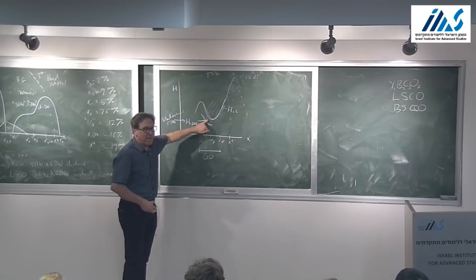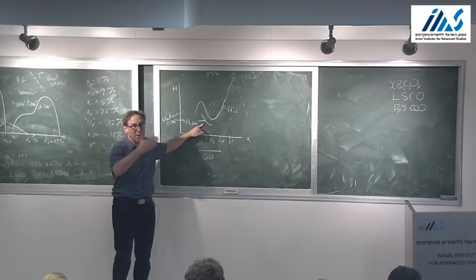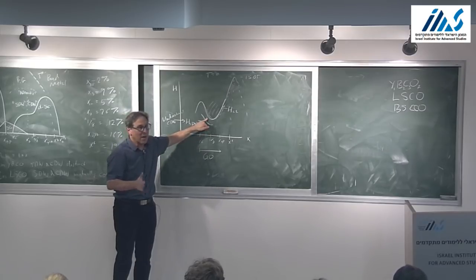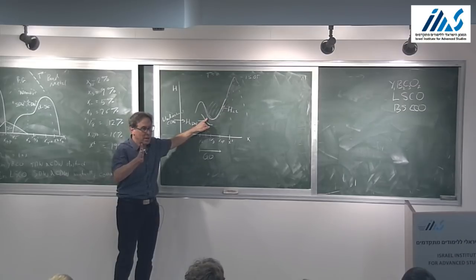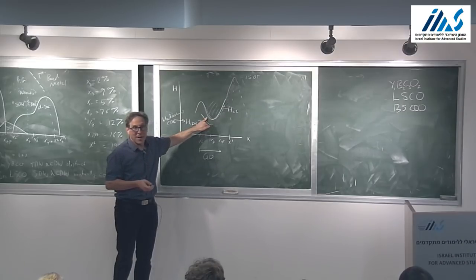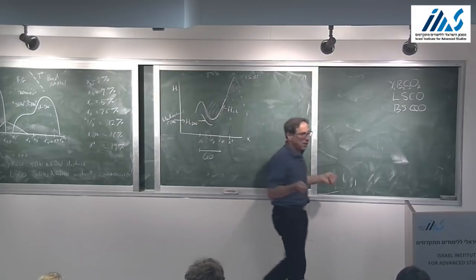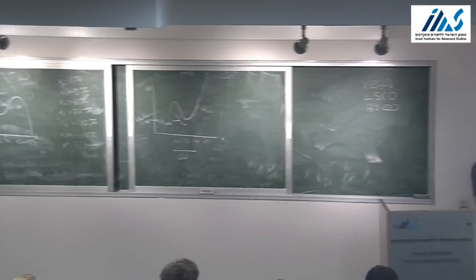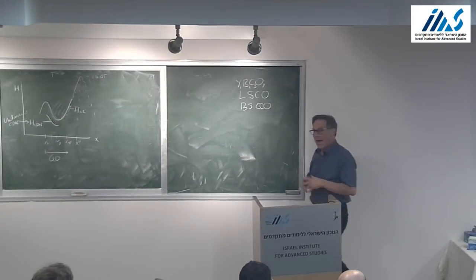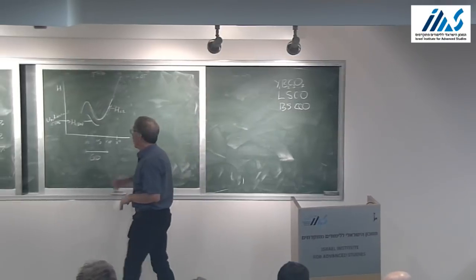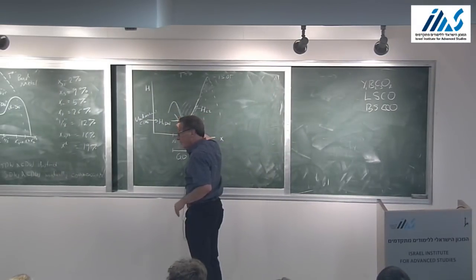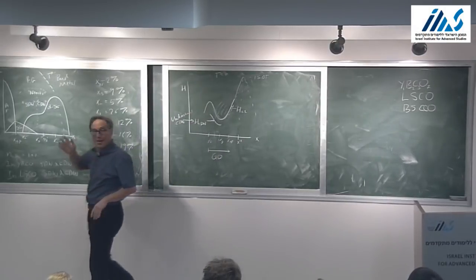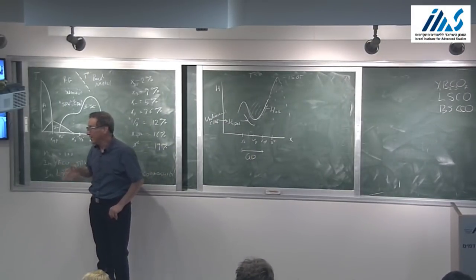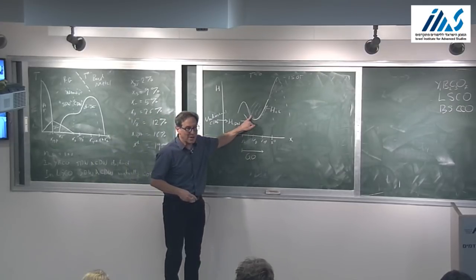Now, there still could be a phase transition here, there could be a nematic phase transition. As I said, down here, the charge density wave is more or less of equal strength in the two different crystallographic directions. Here, on the other hand, the charge density wave is only in one direction. So this could be a spontaneous nematic transition with the charge density wave correlations going along for the ride. That's actually what I think is going on there. However, that's rounded by something else. In YBCO, where it's seen, it's rounded by the fact that the crystal already breaks that symmetry. So this, again, can't be a sharp phase transition on those grounds.